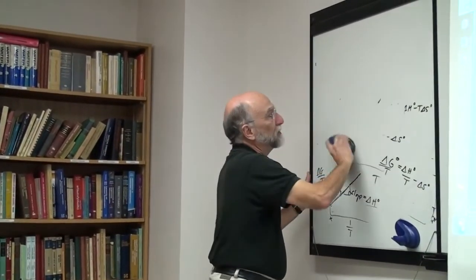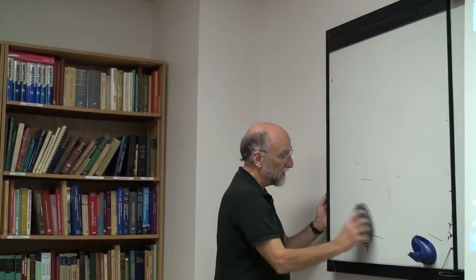Alright, so you just have to measure the heat capacity down to absolute zero, or very close to absolute zero, and there's all sorts of literature on how to extrapolate the last little bit where you can't measure it. Of course, you have to be sure that you're going down to a perfect crystal at 0 Kelvin, with no residual disorder. If you cool the thing quickly, you'll end up with residual vacancies, maybe residual grain boundaries, and so on. You've got to have a perfect crystal with no residual disorder in it, and you have to get close enough to absolute zero. Then there are ways of extrapolating based upon the physics of vibrators and so on, but we won't go into that. But this is a pretty well-established technique, and that's why people worry about measuring heat capacity at low temperature.